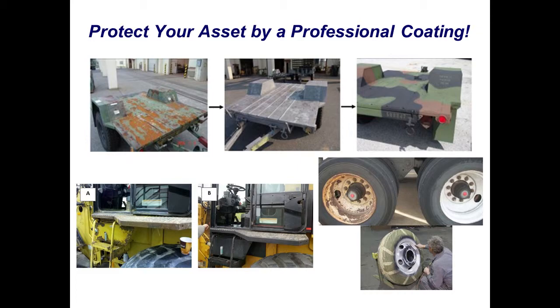Now, coating, like we mentioned, nowadays the coatings are getting really complicated. A lot of them were targeting a much more demanding environment than ours, which is equipment on the roadway. One thing I forgot to mention is corrosion actually goes relatively slow when it's cold. It's really when it warms up, when your truck goes back into your garage, that's where it kicks in. Because corrosion is a chemical process, the temperature has an effect on it. Or to describe it another way, your electrons and all the other things, chlorides and whatnot, are moving very slowly because they are lazy. They're kind of frozen. They don't move fast. Once you heat them up, all of a sudden they move really fast, and then your corrosion goes really fast. That's the same issue with the bridge. That's why I recommend DOTs wash the bridges during spring, so that the residual salts are not there by summertime. By summer, the corrosion issue is really kicking in.